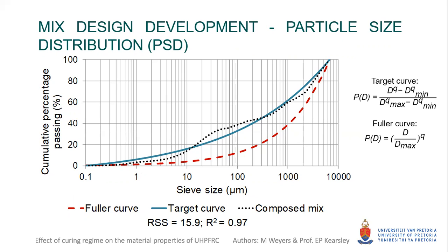The target curve as well as the Fuller curve is also shown by the solid line and the dashed line respectively. It can be seen that the finer particles are better represented by the target curve as opposed to the Fuller curve. The composed mix then serves as the optimized ultra-high performance concrete matrix, which was used for the mixed compositions throughout the study.